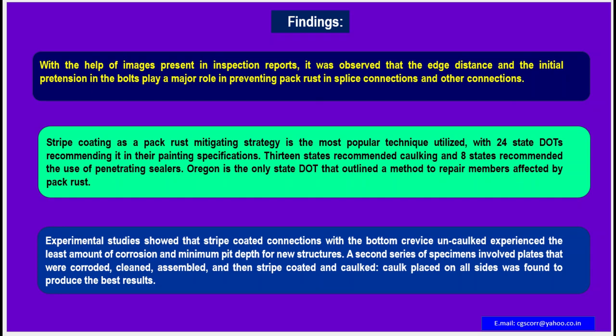Experimental studies showed that stripe coated connections with the bottom crevice uncaulked experience the least amount of corrosion and minimum pit depth for new structures. A second series of specimens involved plates that were corroded, cleaned, assembled, and then stripe coated and caulked. Caulk placed on all sides was found to produce the best results.